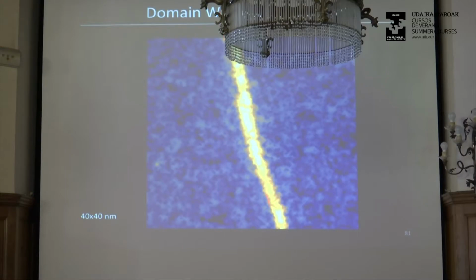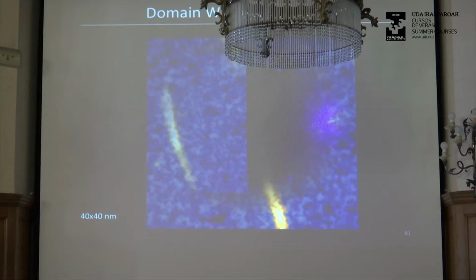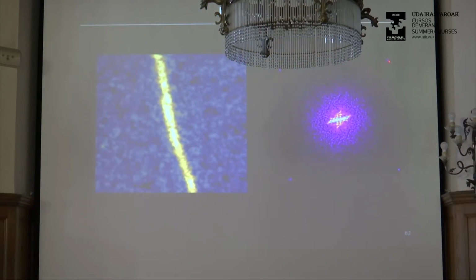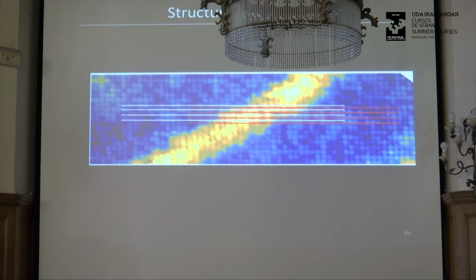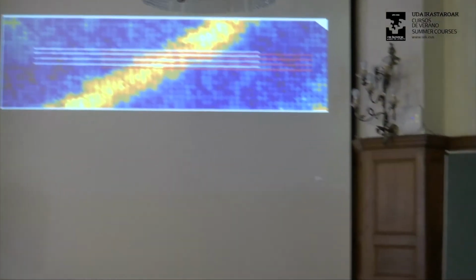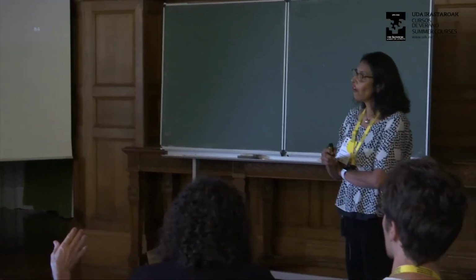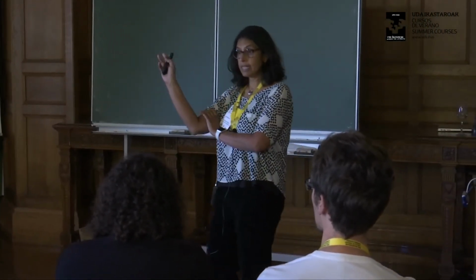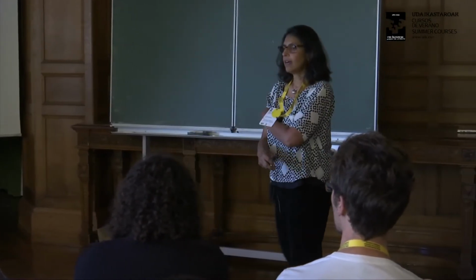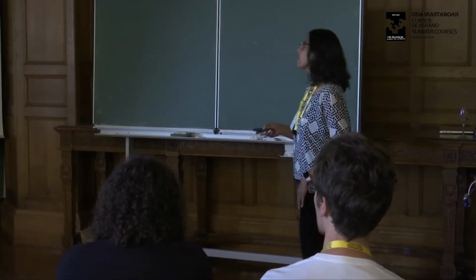So here's another domain wall, and in fact, I'll tell you, this is the right kind of domain wall that we're looking for. If you do a Fourier transform, if you zoom in here, you can see the split peaks in the Fourier transform. That tells you that there's some kind of a phase shift between this side and this side in the atomic lattice. Okay, this is just the atomic lattice. You mean crystal structure? Crystal structure. Okay, not magnetic. No, crystal structure. There's no magnetism in this compound. Yeah. Even though the end member has. Yeah.